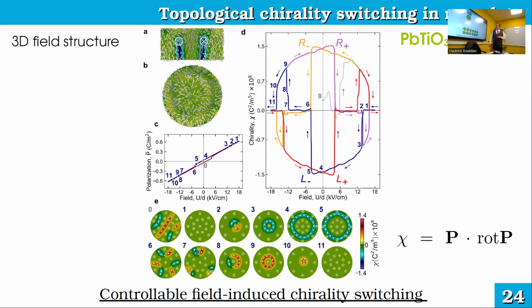What is especially interesting, taking any state, you can come to any other state. Here, the chirality is depicted from the bottom of the nanodot, because from the top it always looks like a fountain distribution, and here chirality is concentrated near the center again. Going through this electric switching protocol, you can achieve any of these states, and all the states are distinguishable. One note to make here: if left and right chirality can be distinguished by light, then up and down direction of polarization, of course, needs some other technique, for example, PFM, piezo force microscopy, but again, for such a case, it can be a fairly simple setup.